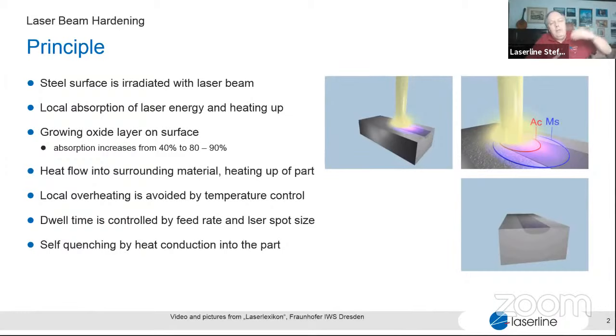So that's why we can even do hardening at low level carbon steels. Low level means maybe 0.15% of carbon. We can get the max of hardness that's possible with even this low content of carbon. So that's very specific for laser. And the other very specific thing for laser heat treatment is that we can apply the laser very locally. That means we do just the heat treatment where it is necessary. And the overall heat input is down to the minimum. And so at the end, the resulting distortion is down to the minimum.